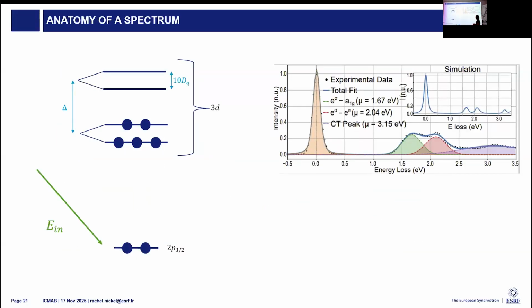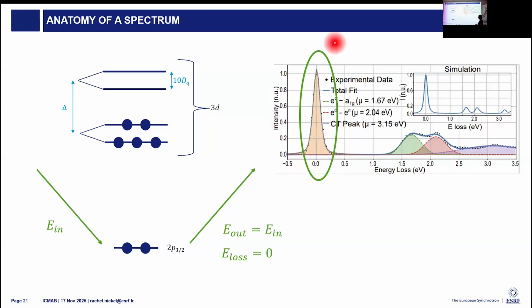So I have on the right an example of what a RIXS spectrum looks like. I'm going to show on the left how these features are produced. So the most simple part is the elastic line. We have a photon in that excites our core hole. The electron sits in an empty valence state, and then it drops right back down. So the total energy contributed to the system between the initial and final state is 0, and that shows up at 0 in our energy loss.